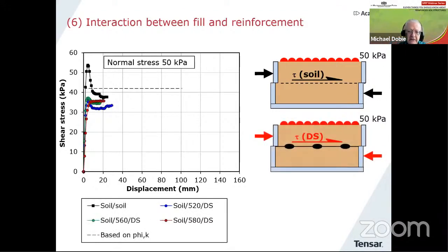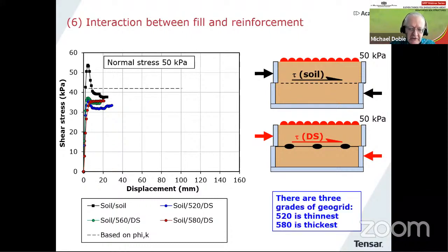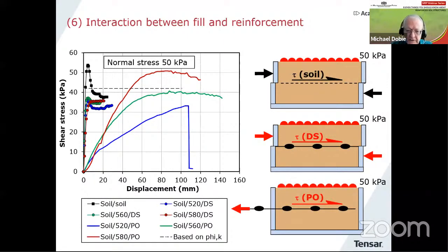We then add to that diagram the sliding interaction tests. And you can see that they don't quite get that sharp peak, but after some displacement, they end up at shear stresses slightly less than the soil by itself, which is what we'd expect, and that gives us the interaction factor. But when it comes to pull-out, again, just looking at the shear, just to remind us that we have 3 grades of geogrid. You can see them there in the legend, a 520, 560, and 580. Basically, the 520 is the thinnest and 580 is the thickest. So when we look at the pull-out test, it looks like this. We're looking at the shear on one side only, and we get those lines. Now, the reason why we go to much bigger displacements is that the displacement is measured at the clamp.